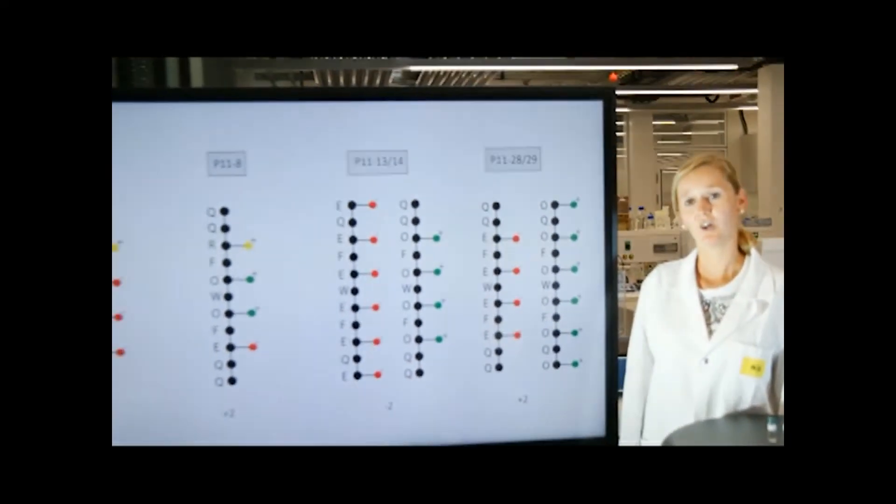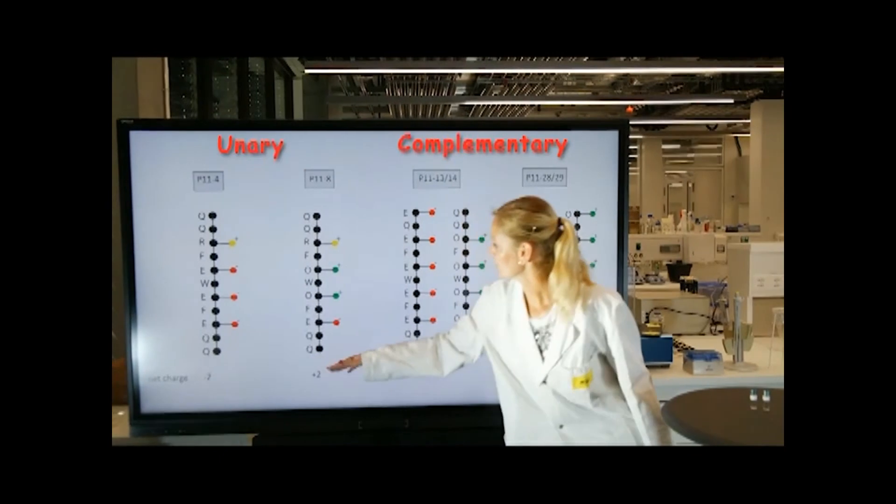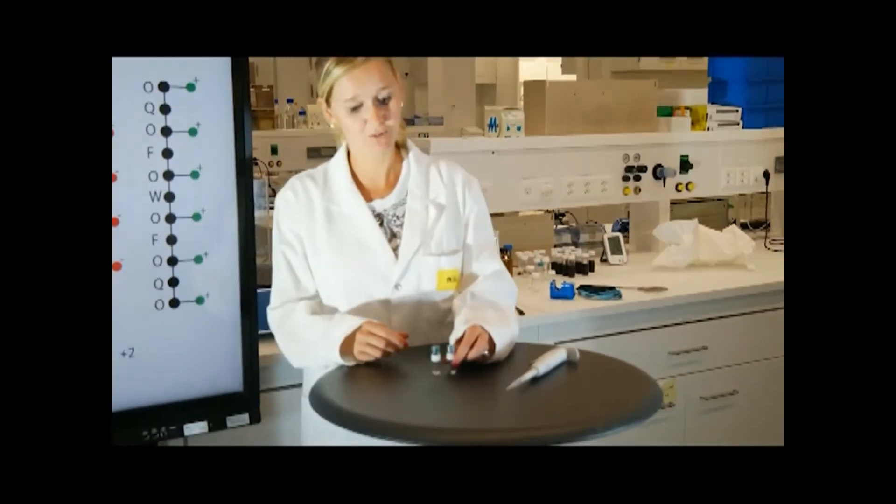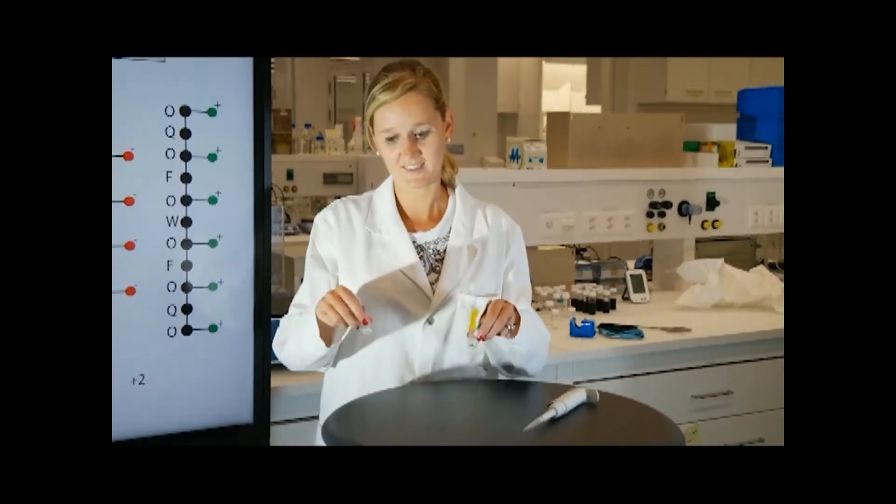From the P11 library designed by Aggeli et al., we selected two unary and two complementary peptide systems. They are biocompatible, non-cytotoxic, and can assemble in an easy and fast way. I demonstrate this here on the P11-28 and 29 system.